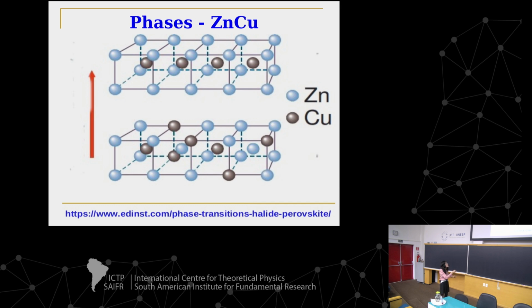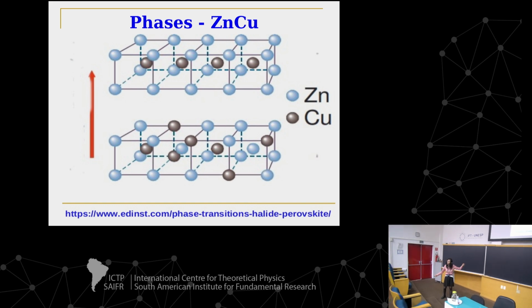You know, because it's in the space that you know. But if you are in another temperature, this position will have a copper. So you see here, before you have the zinc, but now you have a copper because they are swapping positions. So here the order parameter, or the way you measure the phases, is the probability of finding a specific zinc or copper. And this change from this configuration in which everything is fixed to this configuration in which they are swapping makes the original crystal structure change.